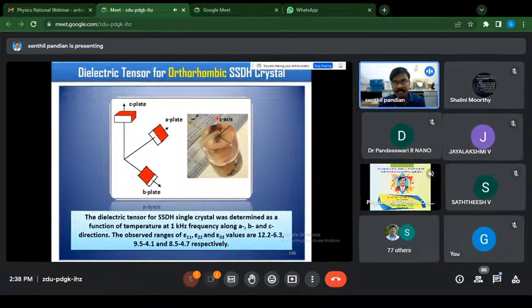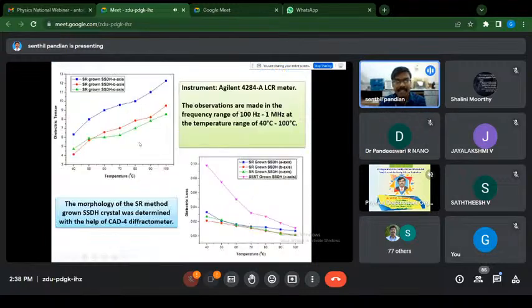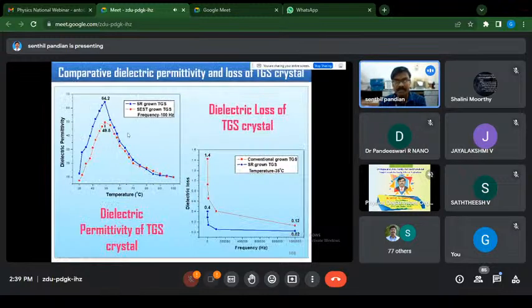But in the case of the SR method, what we have done is we have selected the crystal along its A, B, C directions, and we have cut the crystal for the dielectric measurement. Anisotropy in the dielectric behavior was observed in the SR method grown crystal. Blue indicates the A axis, red indicates the B axis, and green indicates the C axis. The higher dielectric permittivity and the lower dielectric loss clearly indicate that there is no solvent inclusion and higher crystalline perfection of this SR method grown crystal.